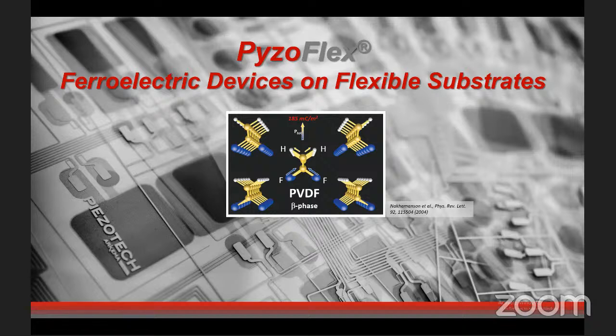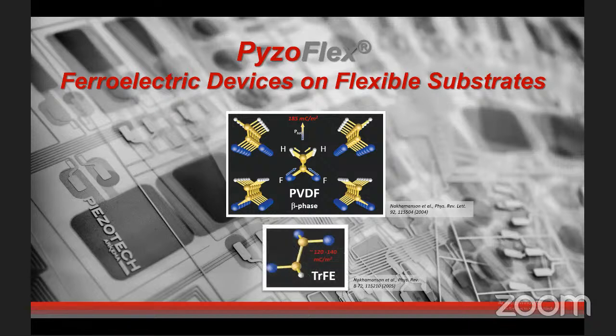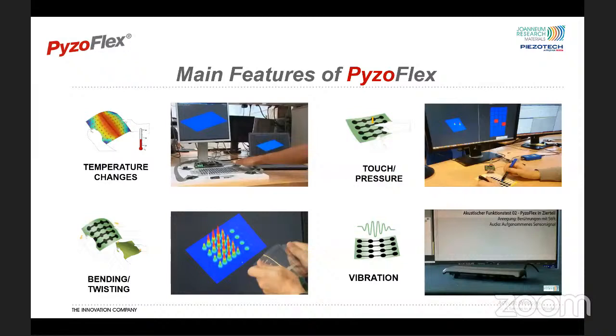In PyzoFlex we use a copolymer of PVDF with trifluoroethylene, which, in contrast to pure PVDF, crystallizes directly from solution in the ferroelectric beta phase. And this is very important for printing, of course. The name PyzoFlex illustrates the essential properties of our technology, namely pyroelectricity, piezoelectricity, and flexibility.